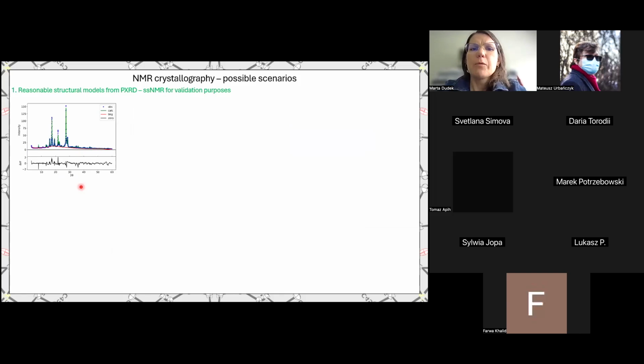So when you think about NMR crystallography, there are actually three main possible scenarios, and people use them in those three ways. You can have a reasonable structural model from either powder X-ray diffraction, indexing, and Rietveld refinement, or from micro ED, and you use solid-state NMR for validation purposes. So you have a ready structural model when you start doing NMR experiments.